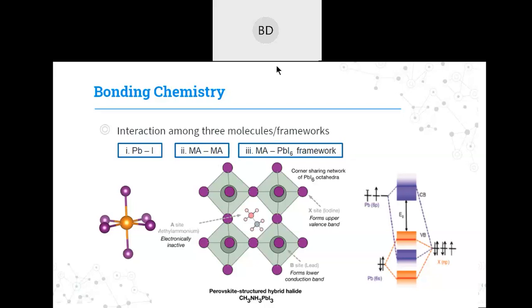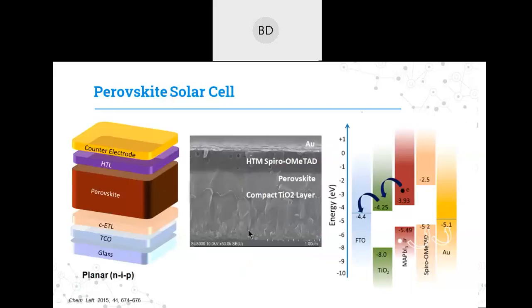Sir, what kind of encapsulation, sir? So there are many encapsulants available, like some polymer materials. On top of the complete perovskite structure, you use some hydrophobic element, so that it can hinder moisture from ingressing into the perovskite. If you use something with a hydrophobic property, it won't allow moisture to penetrate. The second thing is the HTL material; generally people use spiro-OMeTAD. Instead of spiro-OMeTAD, if you use carbon-based material, as discussed in the last presentation by Priyanka, or molybdenum oxide, then also you can increase the stability.